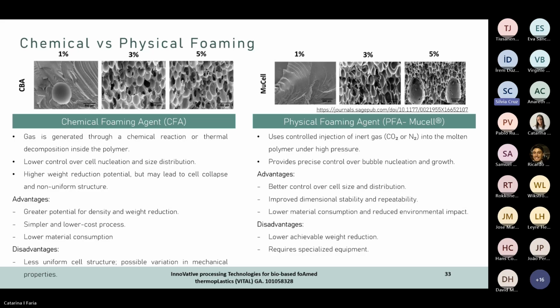Also, the chemical foaming agent reaction may result in byproducts such as water, which can lead to additional degradation of the polymer matrix and the reduction of the mechanical properties. Also, the byproduct can damage the mold cavity, and the mold cavity and screw can suffer from this reaction and be damaged prematurely, which can influence their durability. This phenomenon can be avoided by using physical foaming agents, although it requires more capital investment. However, in the long run, the physical foaming agents will become advantageous when compared to the chemical foaming agents.